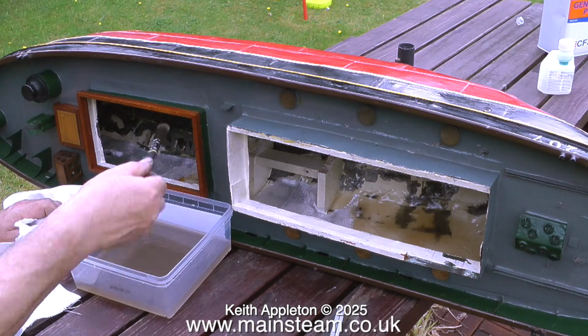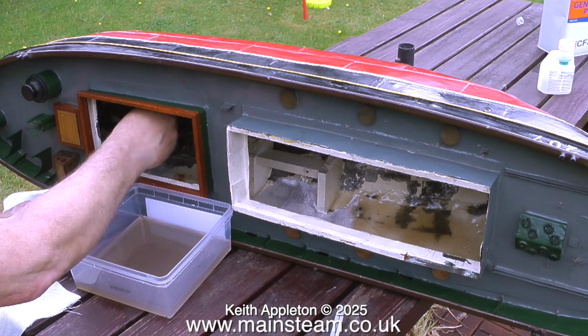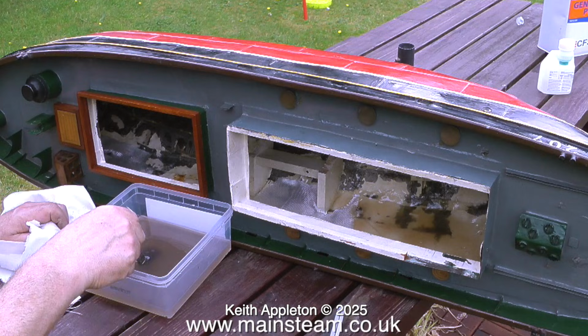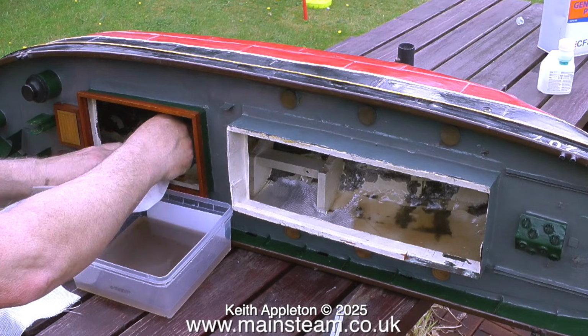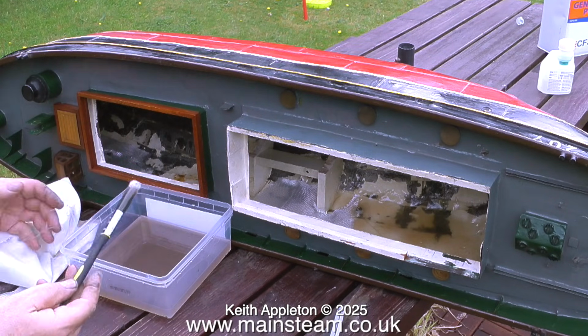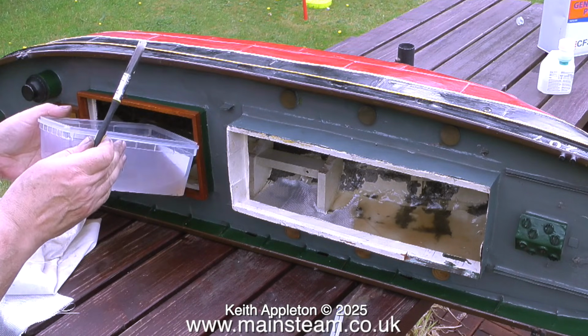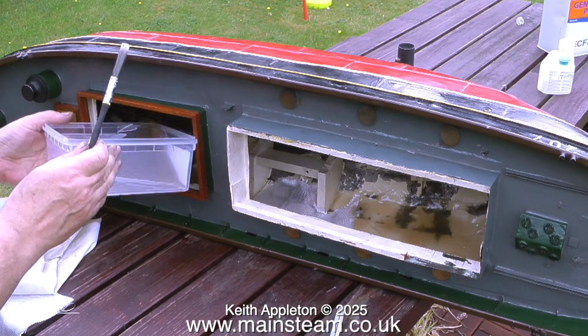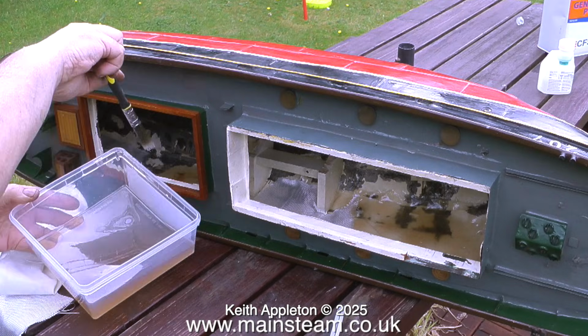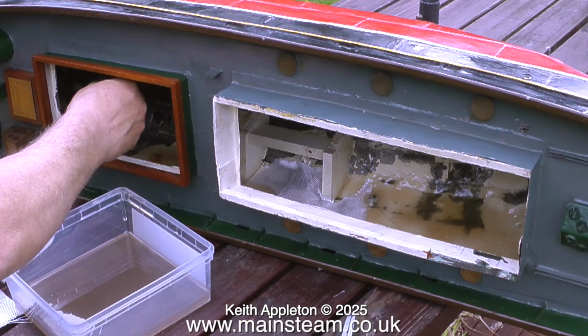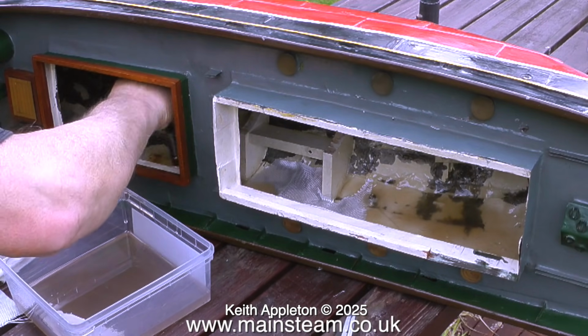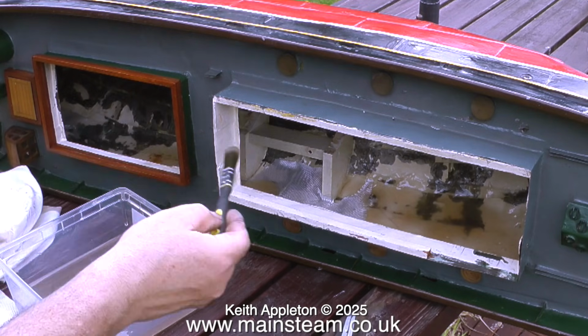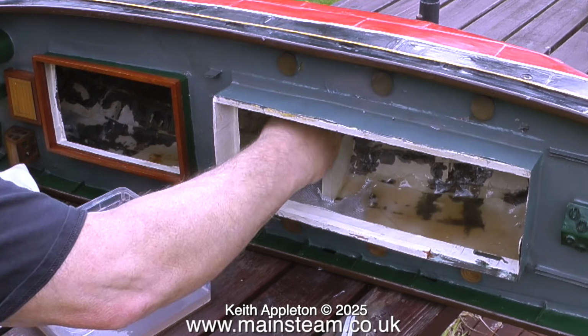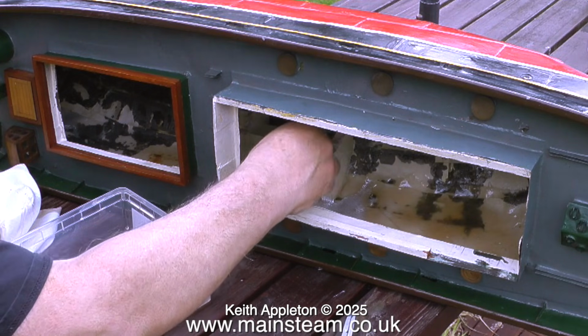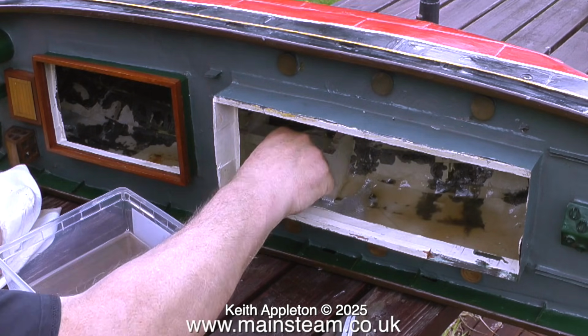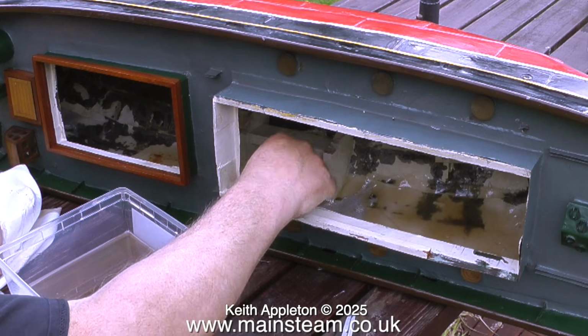A quick note for those of you who like making boats, don't use this stuff if you're bonding parts to small model boats because the glass fibre of the hull is quite thin and the heat generated by this stuff curing may distort the glass fibre hull of your model boat. For bonding components inside model boats that are made from glass fibre, I would normally use epoxy products, either epoxy resin and hardener, or I would use a 2-pack putty such as Milliput or the excellent JB-Weld. That is really strong stuff, especially if you use the 24-hour version.